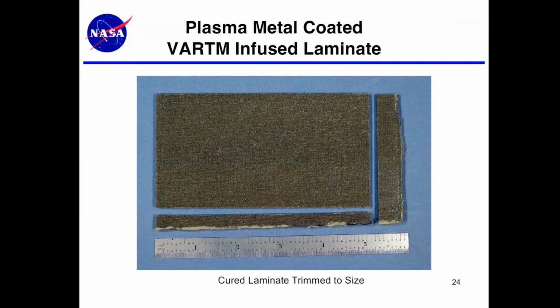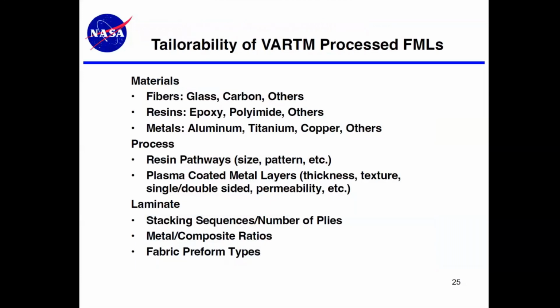This is an example of... I believe we used 4 layers of metal coated fabric here, and then did a VARTM infusing to make the structural material itself. We were able to get high quality by this process. So the next chart, please. Okay, the quality of the part was very good, kind of similar to the GLARE type materials. We had essentially 0 void content, and all the voids in the metal were wet out as well.